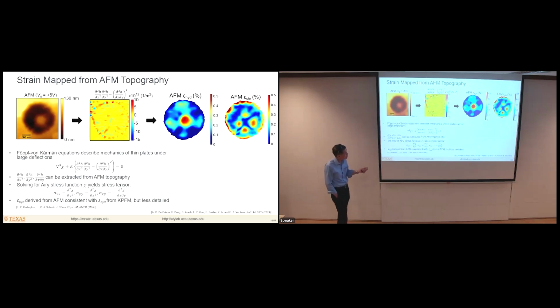Once you have that, then if you look at the second derivatives of that, that gives you the stress tensor, which then you can combine with the elastic stiffness constants to get the strain. All right, so that's the basic idea. And if you use this approach, just from the AFM topography, you get this distribution here for the hydrostatic strain. All right, up to values in this case of roughly 0.5% strain.